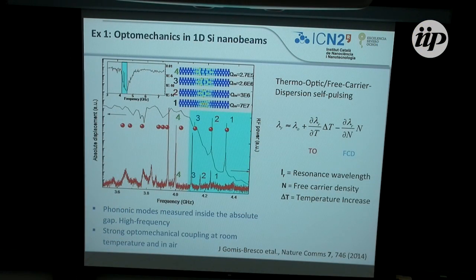So the optical signal affected by this interaction gives you peaks in the structure that are associated with the particular modes, the mechanical modes of the system. They appear at frequencies of 4 or 5 gigahertz. So this is a very exciting regime for a number of telecom applications. And we work, as I said before, at room temperature and in air.